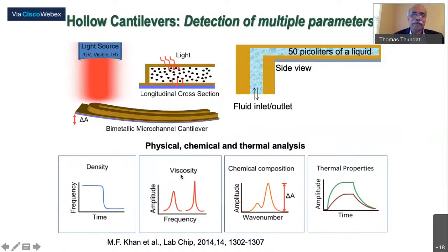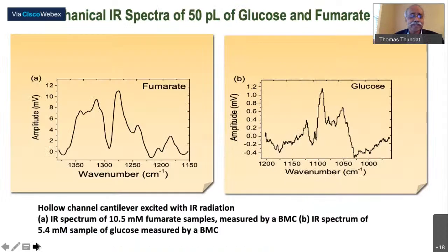You can look at the viscosity. If you look at the Q factor, you can find out the viscosity from it, or you can shine light and get the spectrum like the one I showed you earlier, or thermal properties: shine a powerful laser and look at how the heat is being absorbed, and the decay curve. So all this information, the cantilever can give you multiple information for biosensing as well as chemical sensing. This is the glucose and fumarate inside the channel, this is the cantilever bending, and this is the wave number, and they match pretty well, actually.